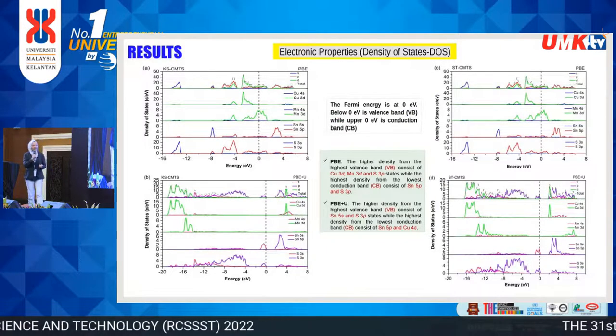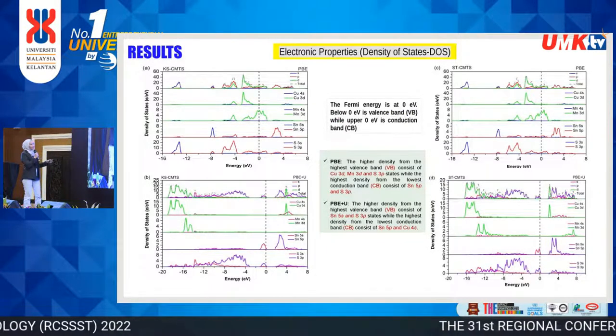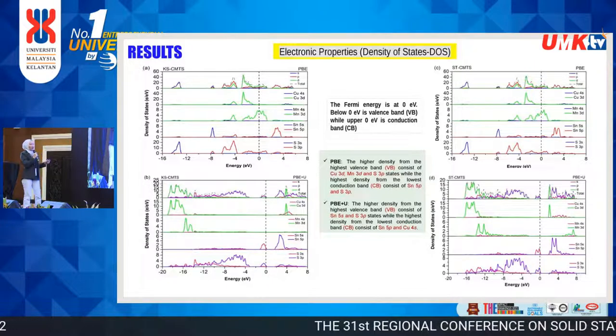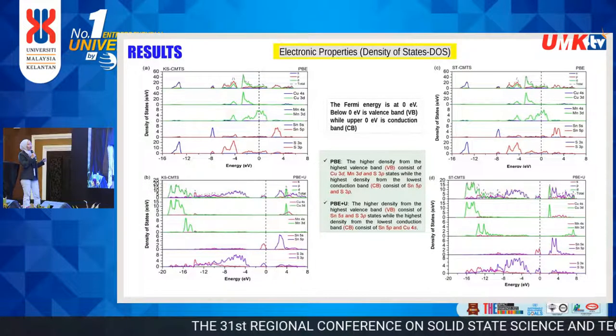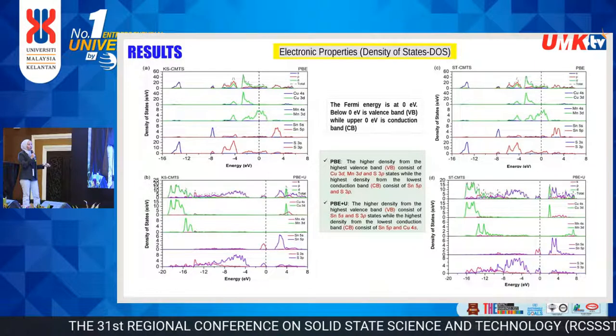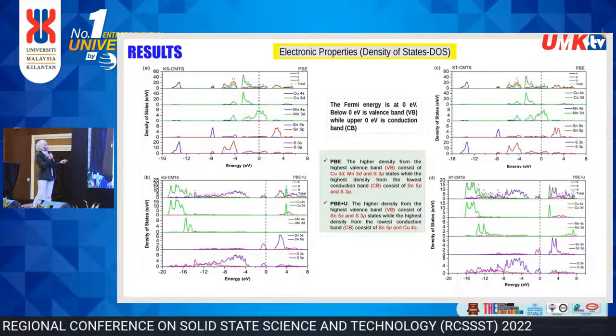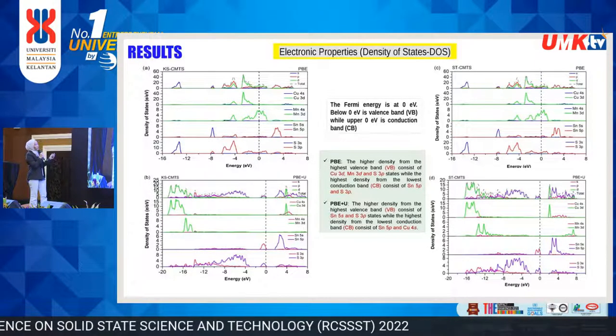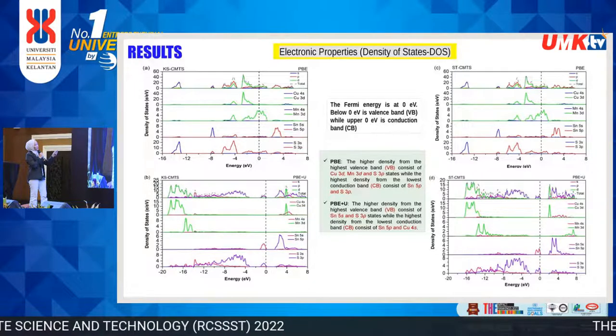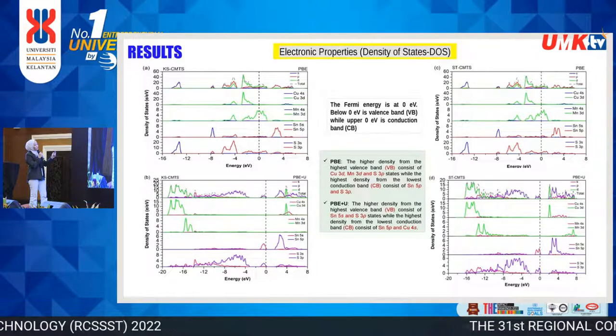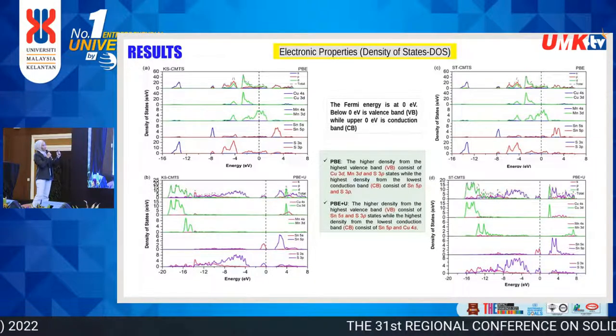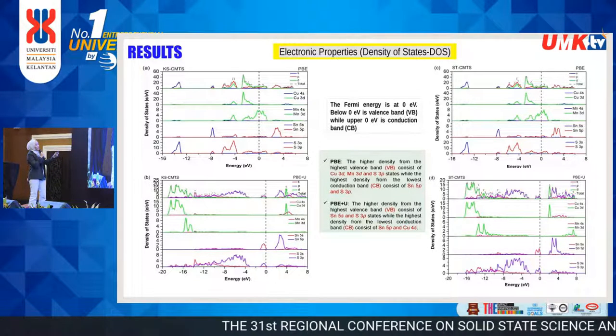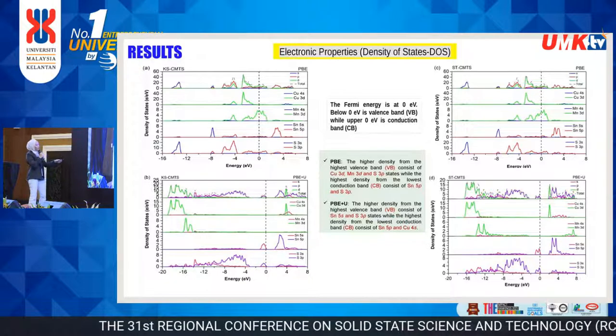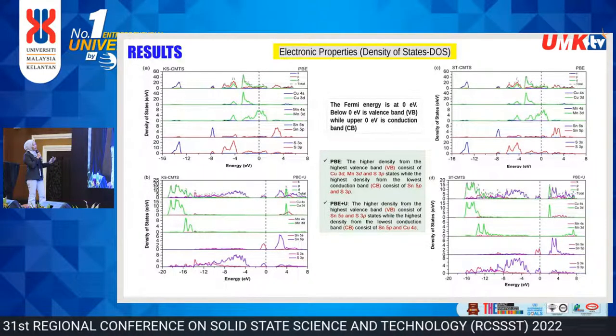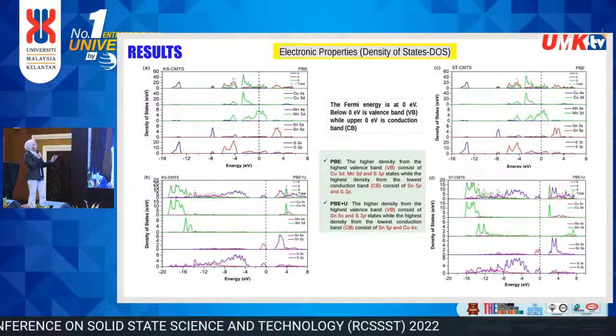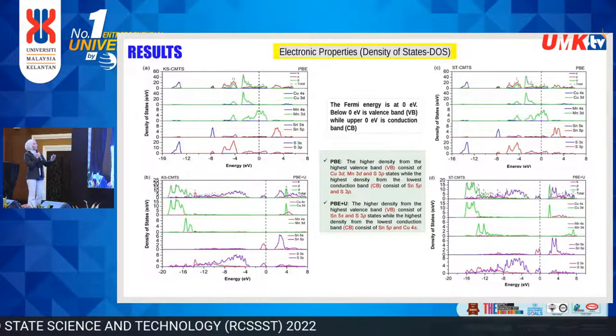So this is the density of states, which we can use to explain the orbitals that occupy the conduction band or the valence band. From here, we can see that with standard DFT, there is overlapping of electrons at the Fermi level, while after the Hubbard U is applied, there is an open gap, or shifted states, at the lower conduction band.